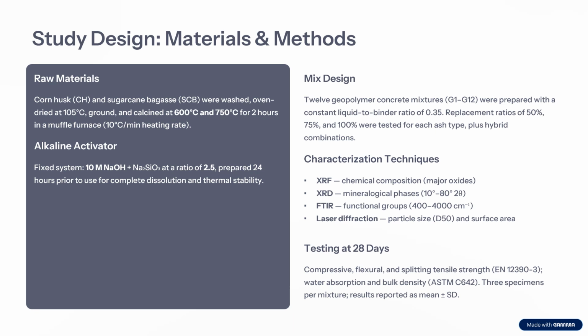After that, we perform compression, flexural, and tensile testing after 28 days, and also water absorption and bulk density following the standard ASTM C642. Three specimens per mixture were tested, with results reported as mean plus or minus standard deviation.